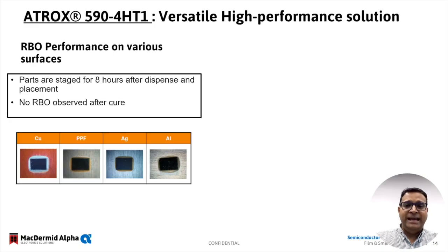590-4HT1 has had a standout performance in terms of RBO control on a variety of surfaces. We have worked with a variety of different customers that have provided surfaces where we have shown and demonstrated that 590-4HT1 has robust RBO performance. Here's an example on the image below where a customer provided us 4 different surfaces, and we were able to demonstrate that even after 8 hours of dispensing and staging, there was no RBO observed after cure.